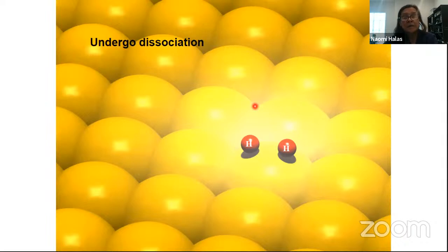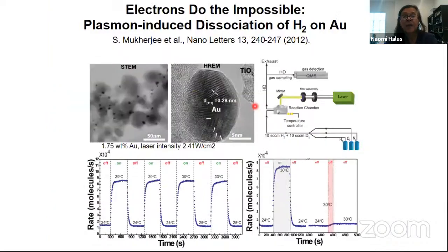And so how do we detect something like this? We detect this by doing a really simple experiment. We flow both H2 and D2. And if we ever measure HD as a function of illumination, if the light is on and we detect HD, this is the only way we could make HD, through the generation of hot electrons by plasmon decay. And so this is what the actual experiment looks like, very small gold nanoparticles. And then we use a mass spec to detect HD.